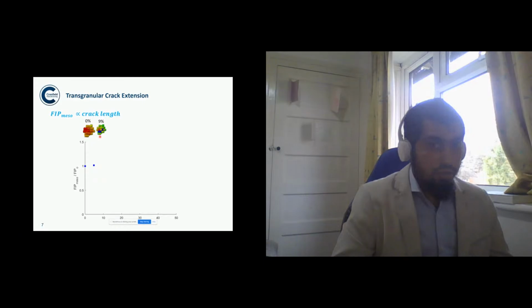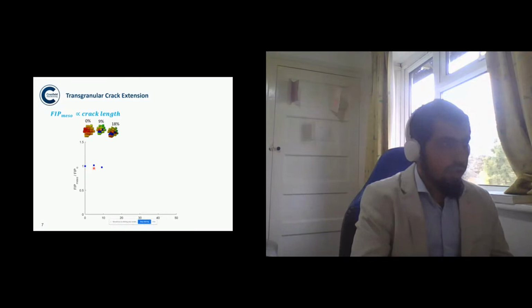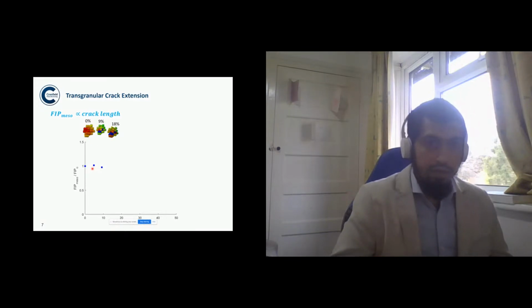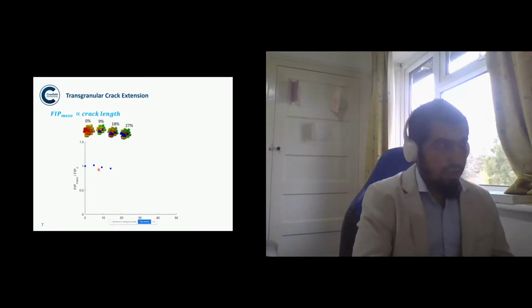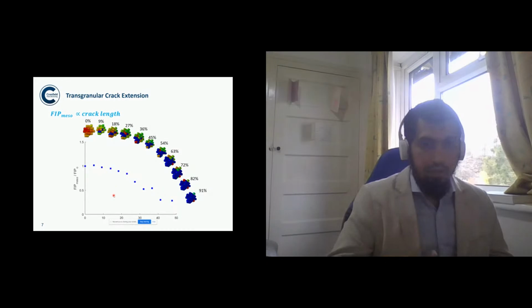So we delete these elements and we average the FIP in the remaining elements, and that is shown by this blue dot in the plot. This is done after every 2 loading steps after the stabilized cycle. So we keep on deleting the 9% incremental elements and averaging over the remaining elements of the band, calculating the driving force, until the full band is cracked. This is the way we extend the crack in the minimum life band, and we study how the driving force is changing as the crack is extending in the minimum life band.